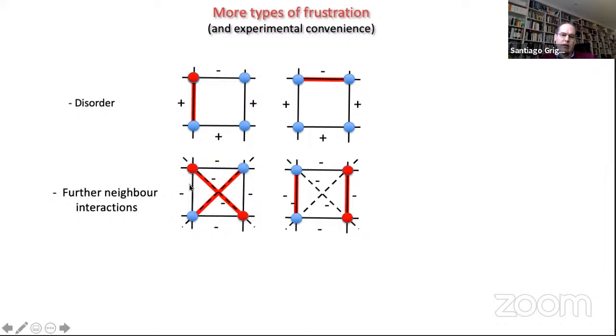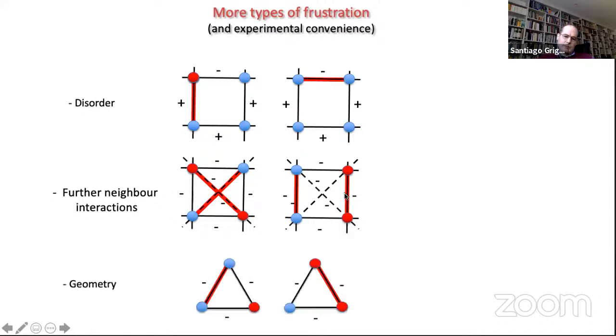So you have an anti-ferromagnetic square Ising lattice, and now you add two more next nearest neighbor interactions, then you see that there's no way in which you can satisfy all of them. If you put an anti-ferromagnetic configuration, the next nearest neighbors are frustrated. If you put some kind of way to satisfy these bonds, you mess the others.